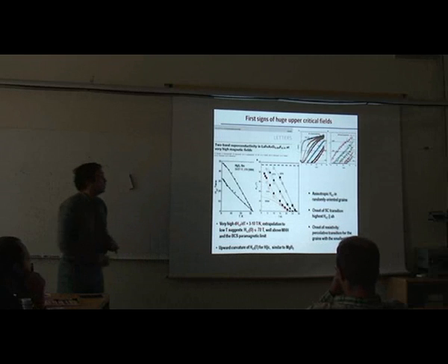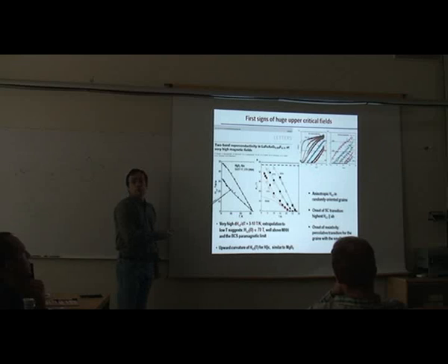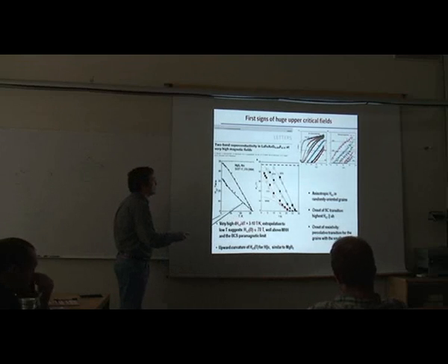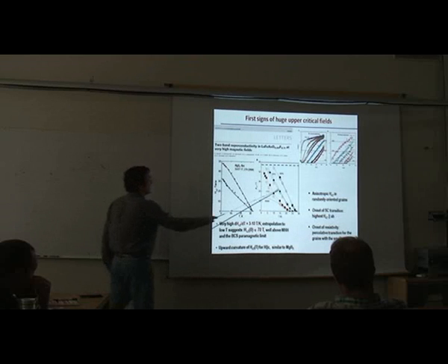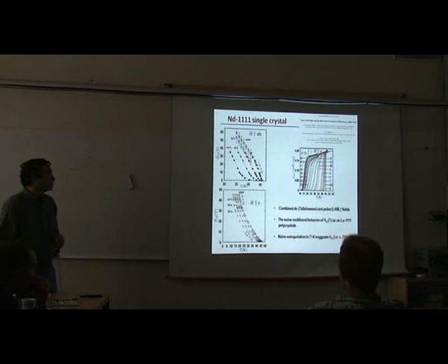When we saw that, we realized that this thing looks very similar to that one. And this is MgB2, a classic two-band superconductor. Again, you can see a pronounced upward curvature for the field along the c-axis, and the behavior like that in the AB plane. The behavior here was very similar. So we concluded that this is a manifestation of multi-band effects.